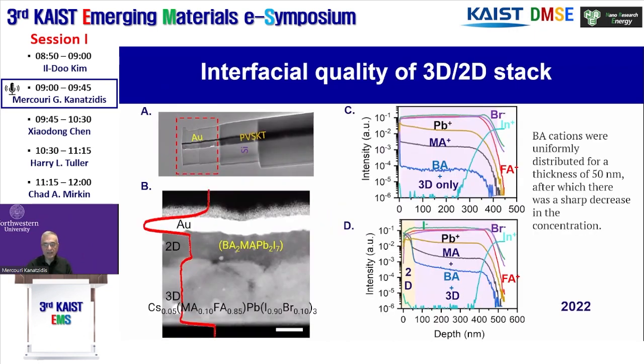This is TOF-SIMS data of the stack. It shows us first, on top you have the butylammonium that comes out. This is a 2D, and then after you exhaust that, you hit the 3D. And so these are well defined and well characterized, as you see here in the left, cross-sectional images.